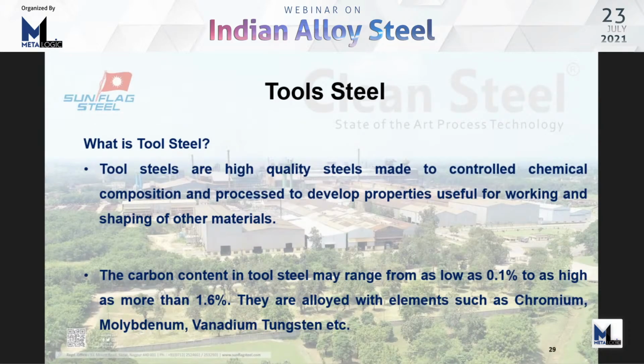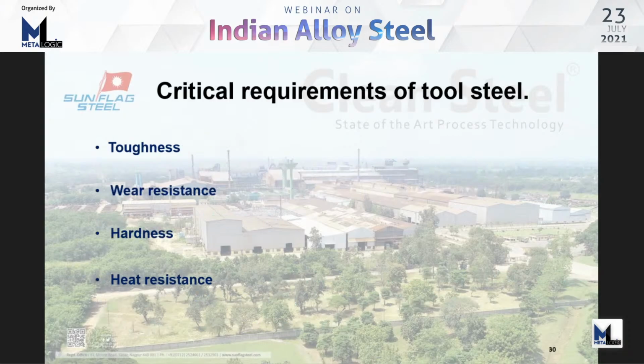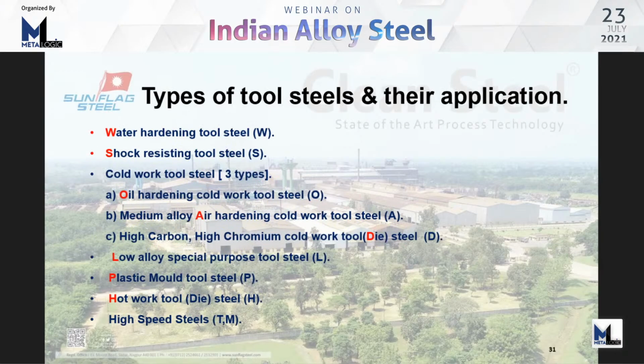Now we come to tool steels. Tool steels are high quality steels made to control chemical composition, processed to develop properties useful for working and shaping of other materials. The carbon content in tool steels may range as low as 0.1% to as high as 1.6%, alloying elements being chromium, moly, vanadium, and tungsten. Normally, tool steels offer toughness, wear resistance, hardness, and heat resistance. The nomenclature in tool steel is such that the application denotes the name. For example, water hardening tool steel as W, shock resisting as S, oil hardening as O, and so on.